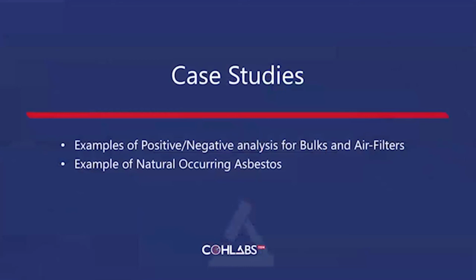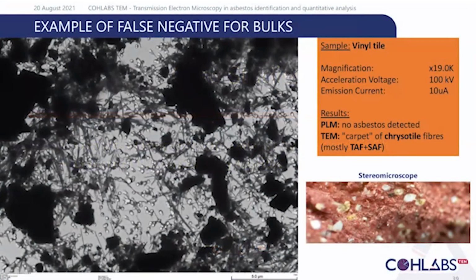Now I'm going to go through some case studies. So an example of bulk analysis. This one was a false negative given by PLM. It's a vinyl tile. As you can see, under the stereo microscope, we can't see any fibers. But once we analyzed this sample with the TEM, we found what we call a carpet of chrysotile fibers. Mostly they were thin and short asbestos fibers, so definitely too small to get detected by light microscopy.